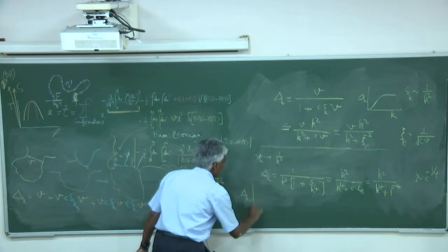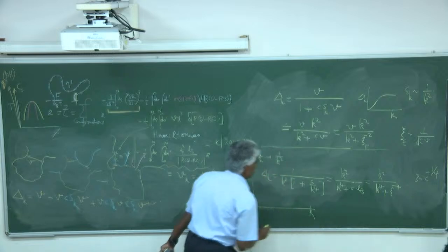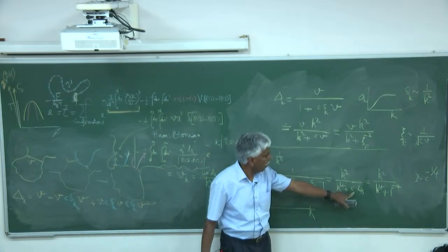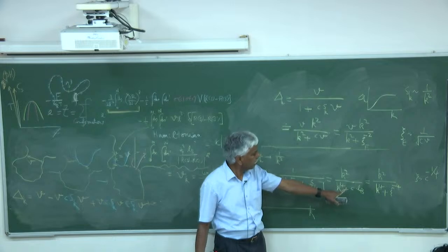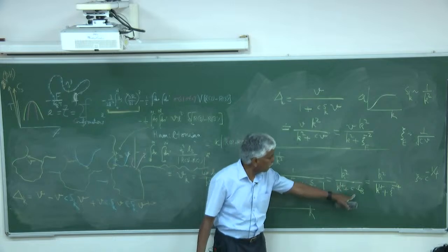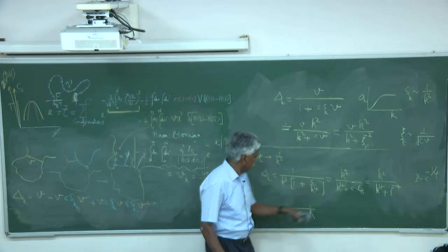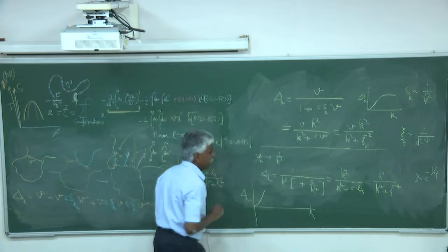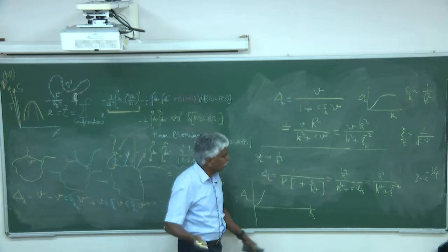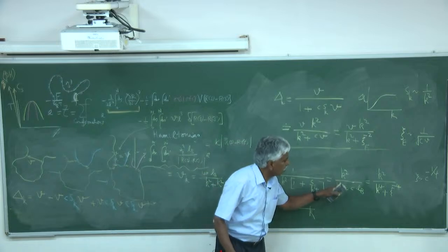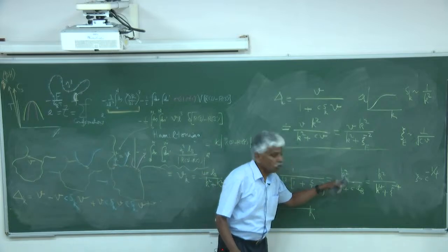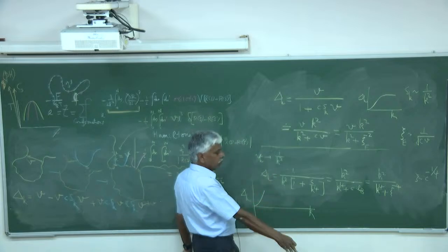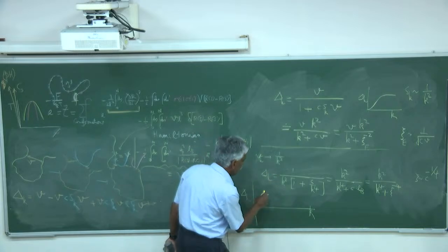That means there is some intermediate length scale, and you can work out what length scale the peak is going to be at. That means there is going to be structural evolution where a finite size structure is selected. It is selected spontaneously. So when the electrostatics is important, you will have what we call the polyelectrolyte peak. We observe this experimentally, well established, and it agrees with theoretical calculations. So there will be a spontaneous selection of certain sizes, certain length scales.